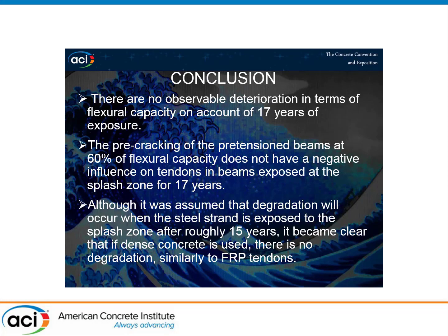Although it was assumed that degradation would occur when the steel strand is exposed to the splash zone after roughly 15 years, it became clear that if dense concrete is used, there is no degradation, similarly to FRP tendons.